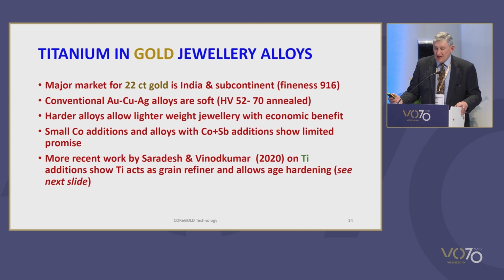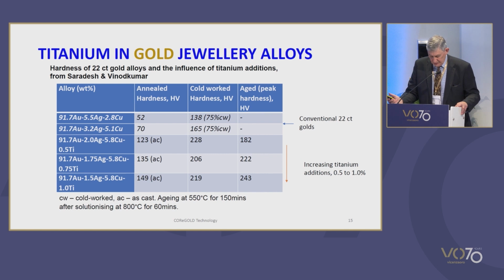But more recent work by Saradesh and his colleagues on additions of titanium to 22 carat gold has demonstrated that titanium additions act as a grain refiner and allow substantial age hardening. Some results are shown in this next table. And we can see, compared to normal 22 carat golds, additions of 0.5, 0.75 and 1% titanium. And we can see in the annealed, in the cold worked and in the aged conditions, we get considerably higher hardnesses. And for hardness, you can read strength as well.